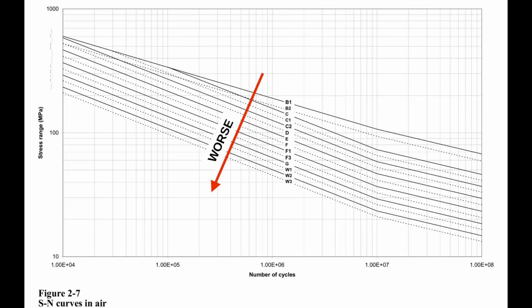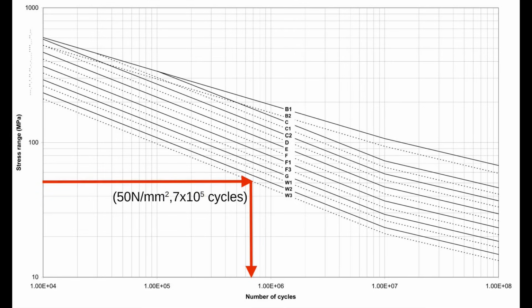I show here the widely used family of SN curves produced by DNV, and this gives the relationship between the stress range and the fatigue life in terms of number of cycles. And the way to use them, on the vertical scale, you go to the stress range which is of interest to you. You look along horizontally until you meet the appropriate SN curve. You then go down vertically and read off the fatigue life on the horizontal axis. And in this case I've taken a stress range of 50 newtons per millimetre squared and found a predicted fatigue life of 7 by 10 to the 5th cycles.